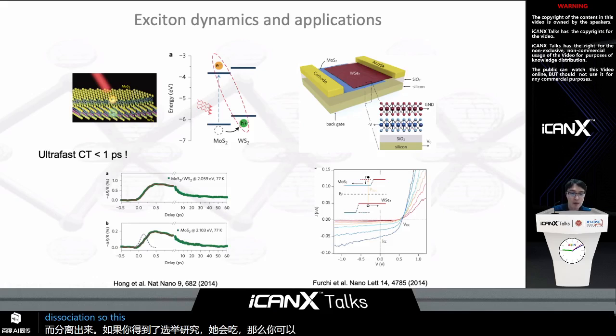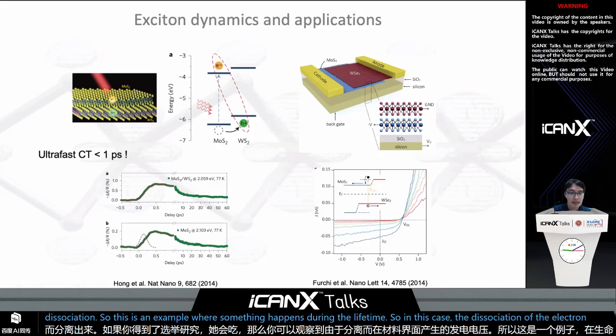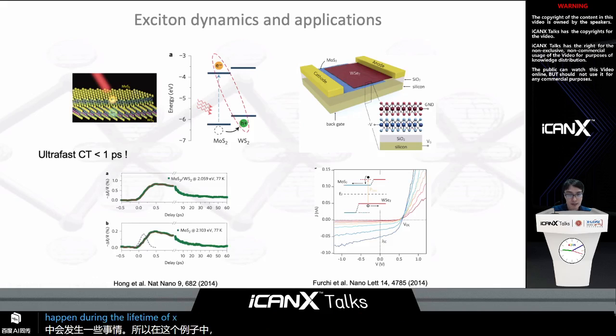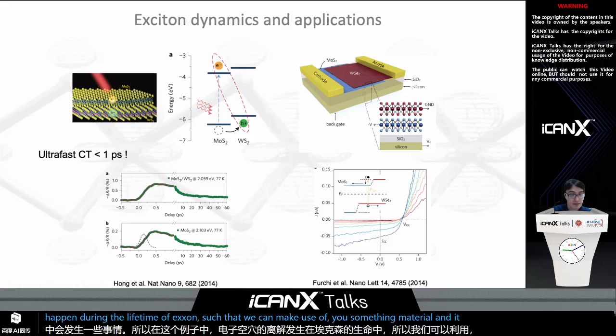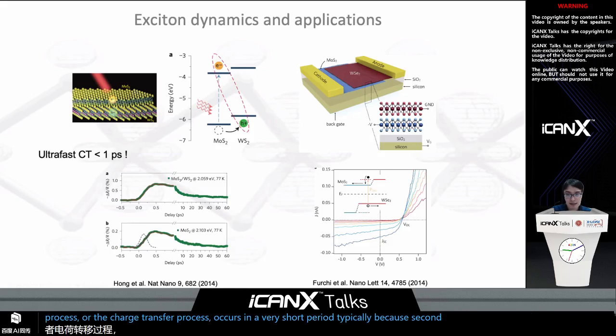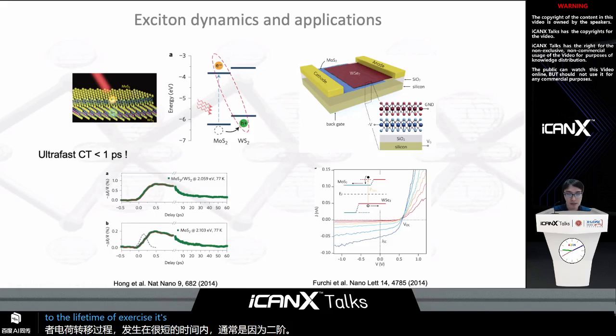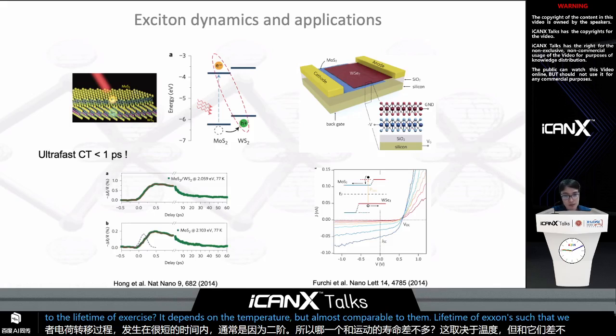So this is an example where something happens during the lifetime. In this case, the dissociation of electron holes happens during the lifetime of the exciton, such that we can make use of the material. And it turns out that this dissociation process, or the charge transfer process, occurs in a very, very short period, typically picoseconds order, which is almost comparable to the lifetime of excitons. It depends on the temperature, but almost comparable to the lifetime of excitons, such that we can, in principle, efficiently generate electron hole pairs or generate voltage in this simple device structure.